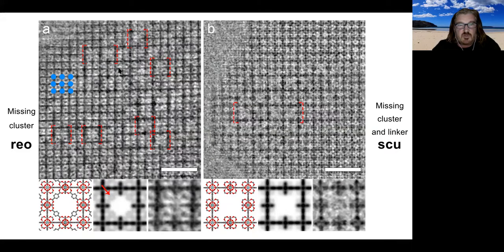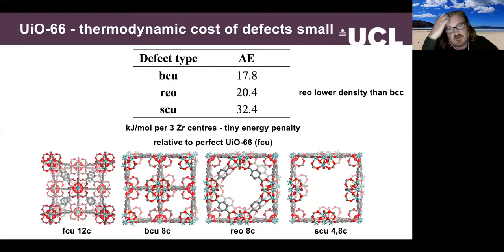So you can see that there's an observable concentration of these defects, which suggests that they might have low formation energy. So this is where we came in, and we've computed the respective energies of forming these different types of defects within the unit cell of perfect UiO-66. All of these energies are expressed with respect to this perfect structure. The absolute formation energies of these defects are incredibly low. These are in kilojoules per mole. And because the energies are so low, we'd expect the concentration of these defects to be high, and that maps onto what we can actually see, because the TEM directly shows you that we have observable concentrations of these particular defects.